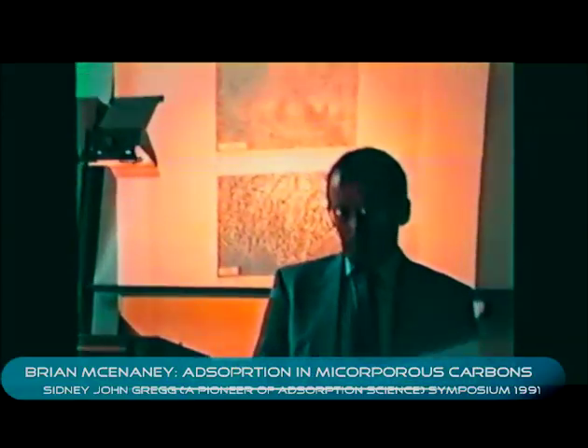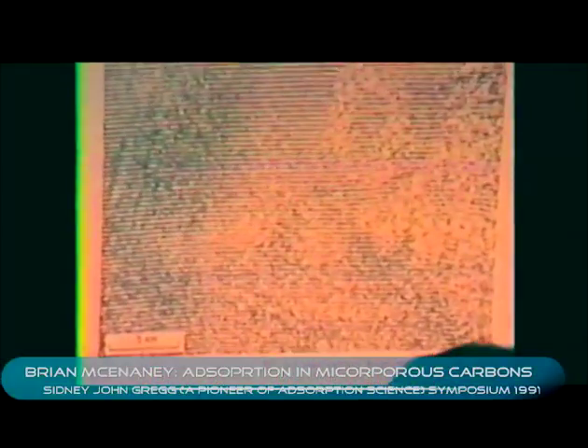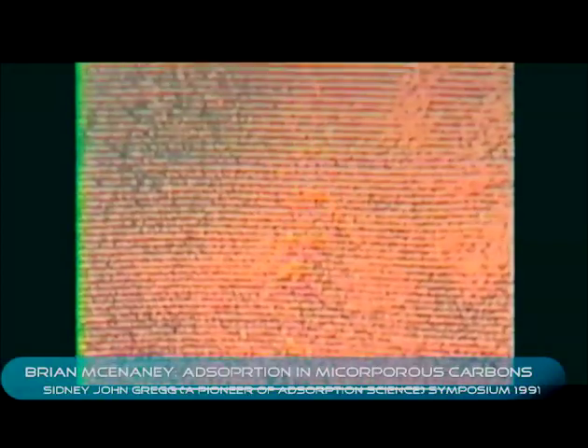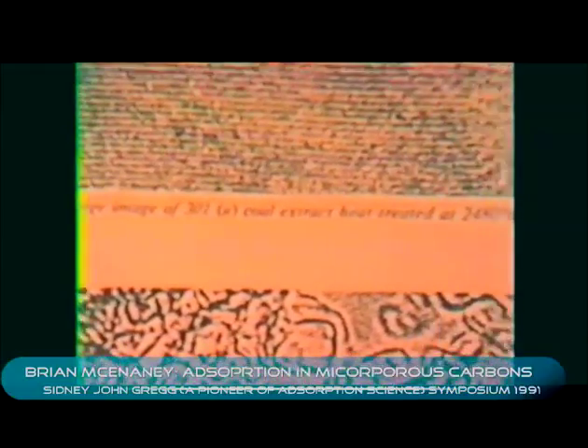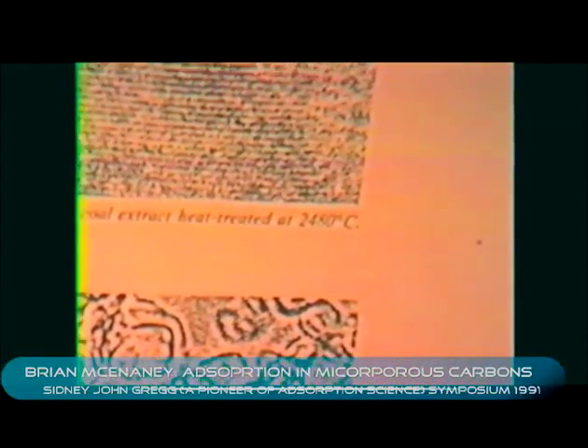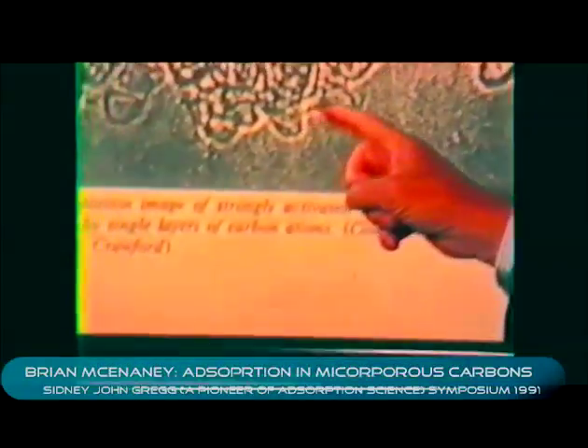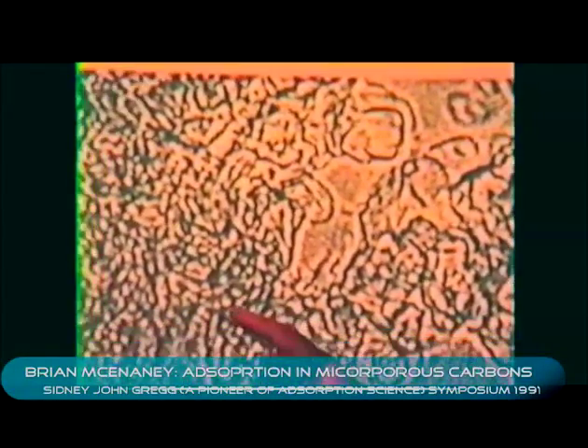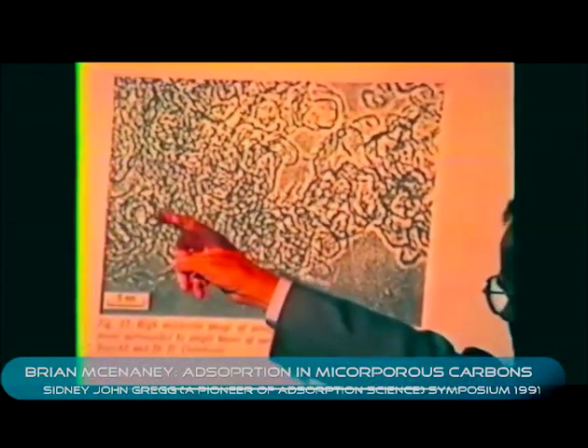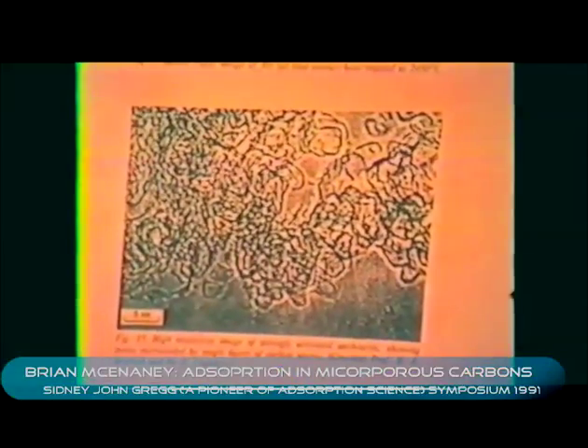Roger's introduced a number of the points that I want to talk about, and hopefully that will save some time. These are some high-resolution electron micrographs. The first one is of a coal extract heat treated at 2,480 degrees C, and it's graphitic. You can see the lines here represent the resolution of the basal planes in this graphitic structure. By contrast, this is an activated anthracite, and you can see that the structure is a tangled, disordered structure when compared with the graphite single crystal.